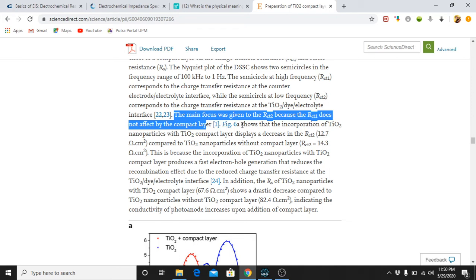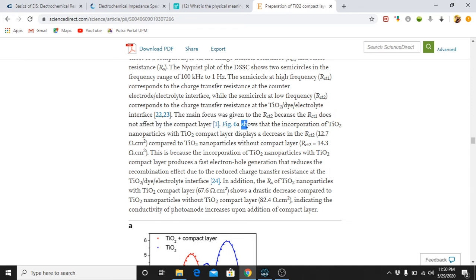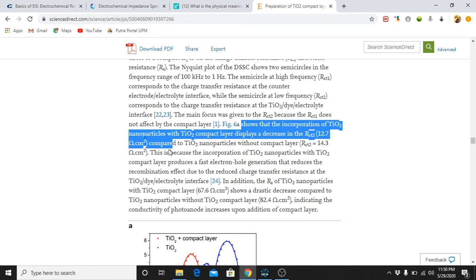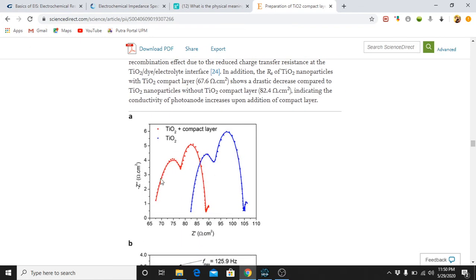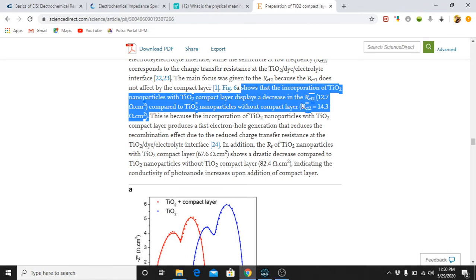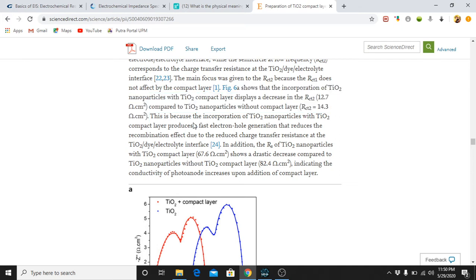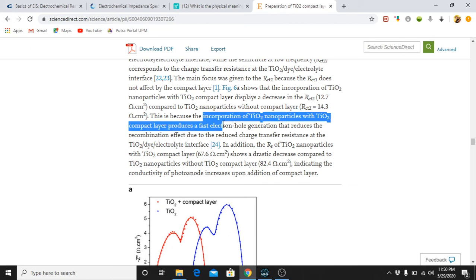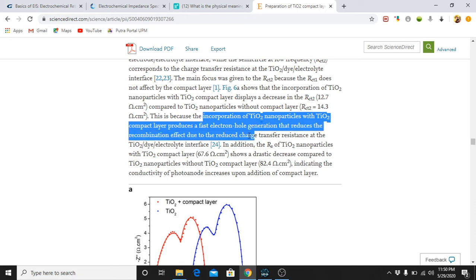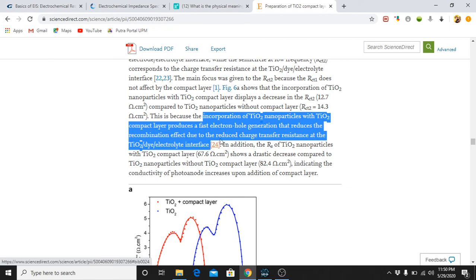Next, from Figure 6, you can see that the incorporation of TiO2 nanoparticles with the TiO2 compact layer displays a decrease in RCT2, from 14.3 to 12.7. This is good because a decrease in resistance is good. We want to have a low resistance. The reason is that the incorporation of the TiO2 compact layer produces fast electron hole generation that reduces the recombination effect, due to reduced charge transfer resistance at the TiO2 dye electrolyte interface.